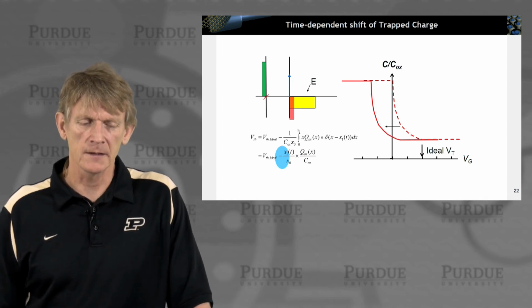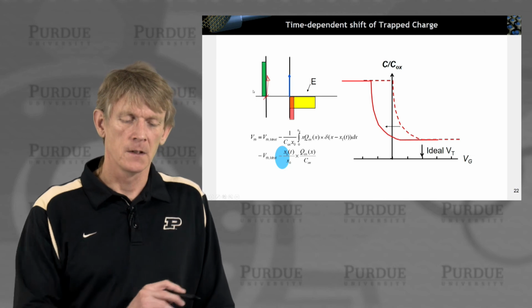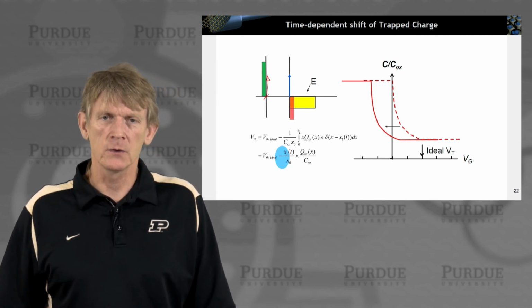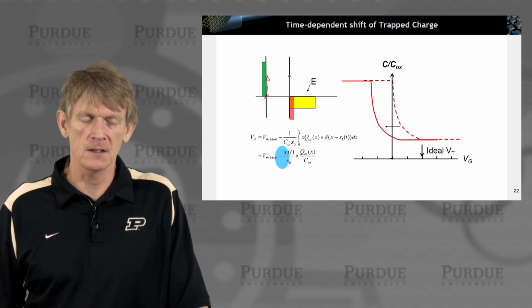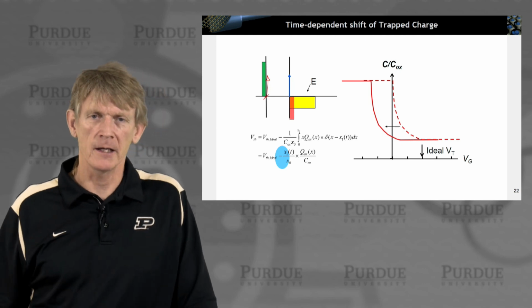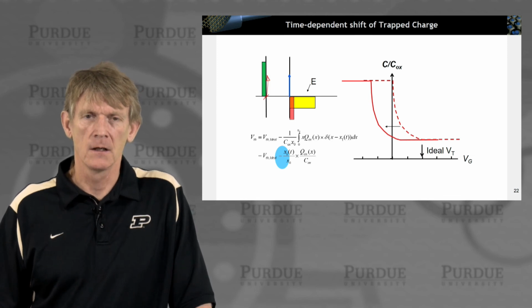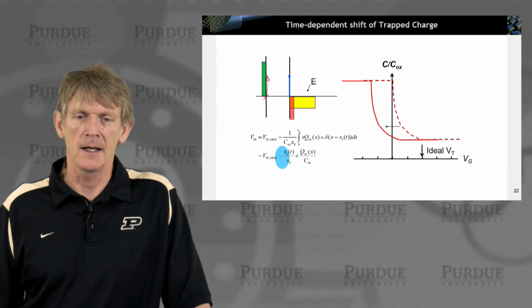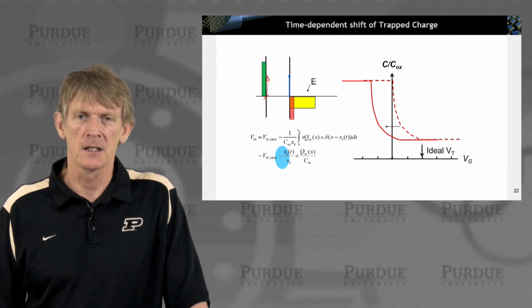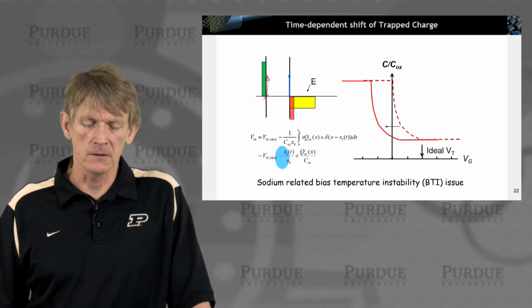All right, and why would positive charge move from the metal oxide interface to the oxide semiconductor interface? Well, in this case here, it's positive charge, and it sees a negative charge being piled up on the other side. Okay, so if that charge were mobile, it'll want to go over to these negative charges. It'll be attracted. If these were individual charged particles, so to speak, or atoms that have a positive charge, they will migrate over there. Okay, so that is in reality a real problem.